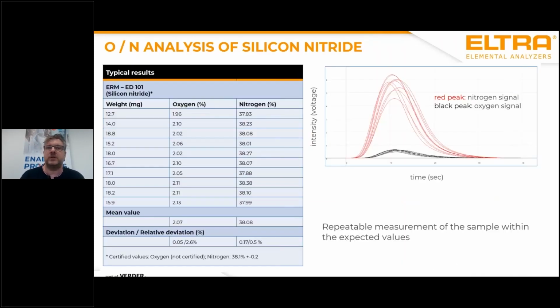And these are the typical results, which means you always get some curves. One curve means the oxygen signal, and this is the one which is here colored black. And then, of course, you also get a signal for the nitrogen. This is the one which is colored here red. And on the left side, you see a typical result table of multiple measurements.